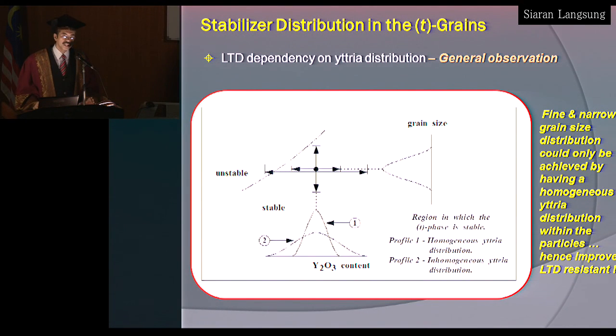This supports the theory which states that in order to have a narrow or fine grain size, you must have a homogeneous distribution of yttrium in the starting material, as the diagram shows for curve 1. The diagram on the extreme right shows the distribution of grain size. So in order to have a stable structure, that's what the theory postulated. If you have an inhomogeneous yttria distribution, as in curve 2, with a wider distribution, there is a possibility of the tetragonal structure being unstable, and it will then transform during LTD, or exposure to a steam environment.